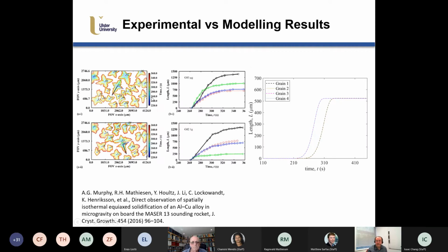And also then looking at the length of the arms, so this is in micrometers. So again, looking in 4 directions and looking at the 4 lengths and getting an average, you would then be able to compare the average to what was predicted by the model. And here's what was predicted by the model. So qualitatively reasonable agreement, and we were getting around 500 microns for the final arm lengths, and that's not so far off from the average if you were to look at the average on these 2 cases as well.